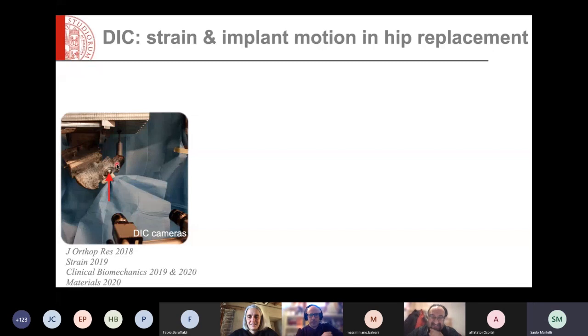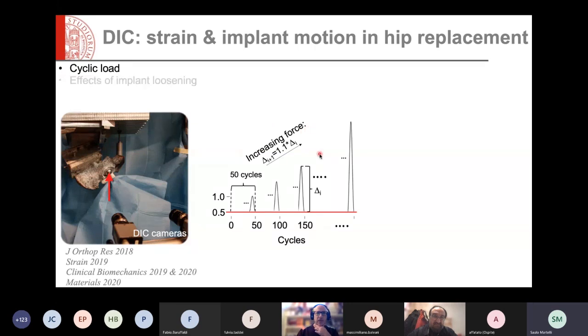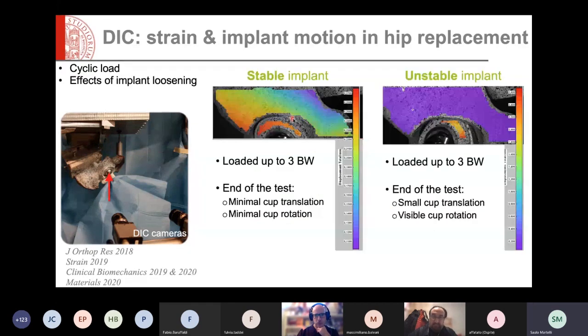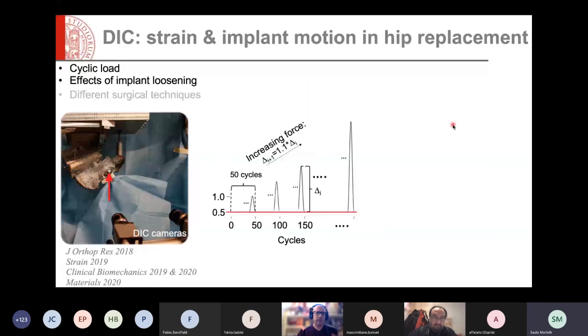So we were measuring the effect of the presence of a hip cup and how loosening under cyclic loading is affecting the strain distribution in a stable and in an unstable implant. And we were also able to measure the displacement. You see that the cap here is quite tilted.